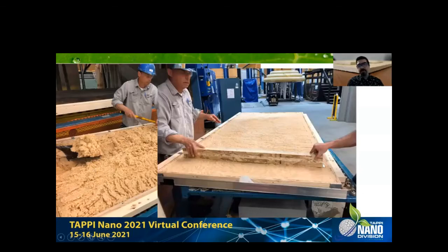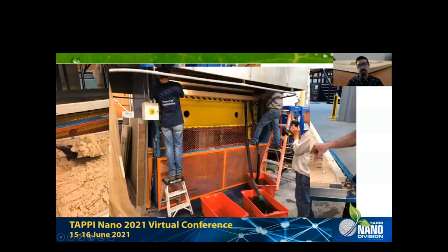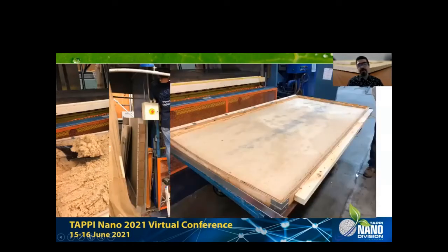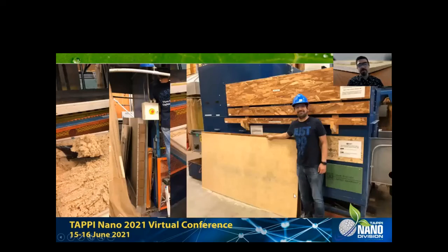This panel was made in the same way, dewatering. This is the dewatered panel, then goes into the press. And there you have, this is the largest particle board ever made using nanocellulose binder, 4 by 8 feet. It has about 15% by dry weight nanocellulose and 85% wood particles. In terms of mechanical and physical properties, it's at least as good or even better than regular particle board at lower densities and medium densities.